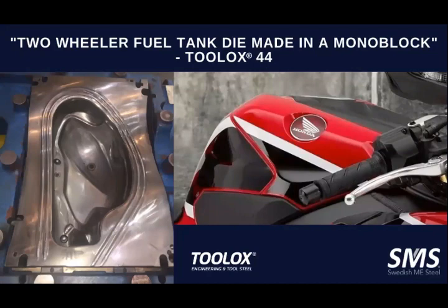So the life of the die being 1 million shots, for almost 10 to 15 times the die has to come out of the manufacturing plant to the nearby city for coating. And there was 2 weeks of production loss every time the die comes out. With Toolox, it was a single monoblock. The weight of the tool was 1 ton. As you can see, we have scooped out almost 500 kgs out of it.